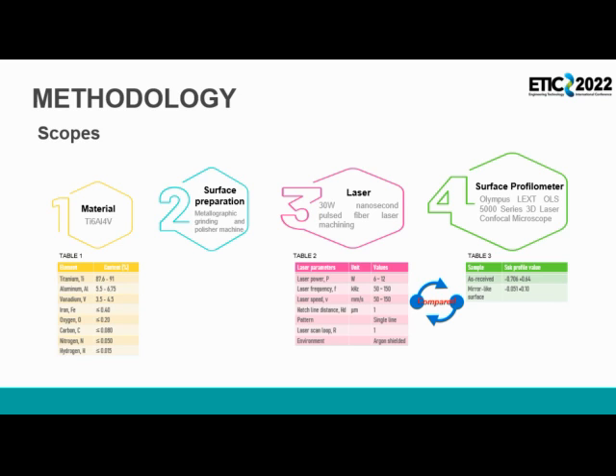The nanosecond laser system from IPG Photonics Corporation was used in this study with the parameters in table 2. The surface topography of the as-received mirror-like surface and laser polished surface were observed using the Olympus LEXT OLS5000 3D laser scanning confocal microscope. The skewness surface profile in the areal distribution profile was taken on average from 3 different areas on the sample with lens zoom values up to 20x.